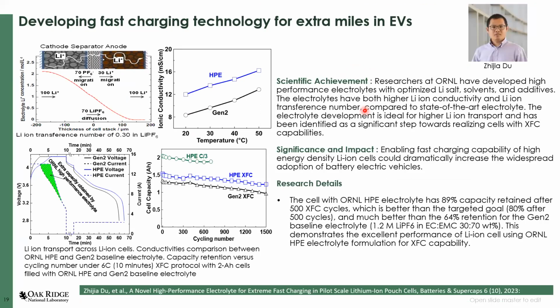In addition to that, we discussed fast charging, the need to be able to charge a battery in about 15 minutes in a car. There's a lot of work going on in developing fast charging technology. One of the ways that one can improve the rate of charging is to tune the electrolyte, which is basically a conduit for taking lithium from one side of the cell to the other. So it should have good properties to move this lithium. Ionic conductivity, lithium ionic conductivity, and lithium transference numbers are important properties that can be tuned.